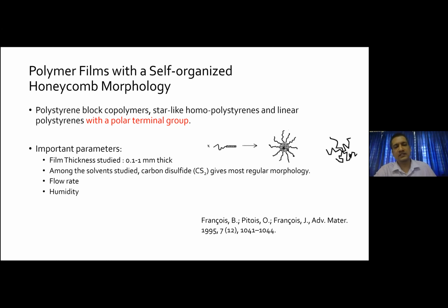Now they used solvents to dissolve these kinds of polymers. Many organic solvents were used like THF, chloroform, and so on. And they found that carbon disulfide gives more regular morphology compared to the other solvents. And the film thickness they used varied from 0.1 to 1 millimeter, and the thickness of film does not have much influence, rather the depth of the well varies as a function of thickness of film during the earlier studies. The flow rate and humidity control the dimension of the pores, or the size of the droplet that is condensing onto the system.